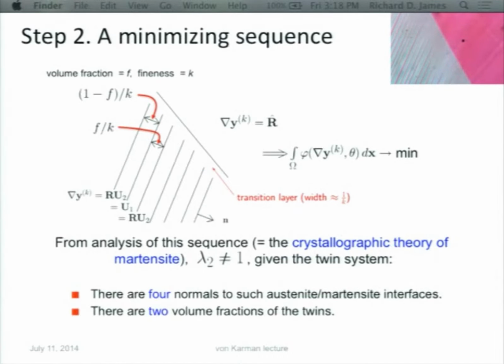So in fact, it turns out that if you give this previous solution, there are 4 normals which work, and they're corresponding to 2 values of F. Okay, so it's quite a rigid calculation. You compare that with experiment, actually it was a big deal because the normal to this is a so-called irrational plane, which means that it does not have small integers as its components in the cubic basis. So that's the result of that calculation. It nevertheless agrees very well in lots and lots of alloys with that calculation.